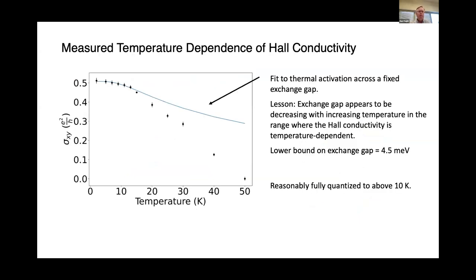We can look at how that varies as a function of temperature. The previous data I showed you were at 4 degrees. We retained the Hall conductivities within a few percent of 1/2 E squared over H, all the way up to about 13 Kelvin or so. And then the Hall conductivity actually remains quite large, all the way up to the Curie temperature of the chrome germanium telluride, which is about 50 Kelvin.